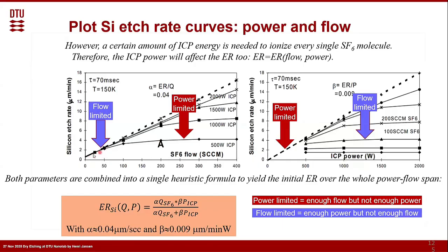Why is that? Well, in the beginning, you have sufficient power at a very low flow regime. There's so much power that all the SF6 will be cracked into fluororadicals, and it means that we call it flow limited. The etch rate will go just linearly up with the flow. But there's a moment where you put in so much SF6 that the power of 500 watts is not sufficient to crack anymore. So a lot of SF6 is just passing by, and it will never get the reaction to create fluororadicals, and it just goes to the exhaust and it's gone. That's where it starts to saturate. Of course, if you then increase the power to a higher value, you fix it at 1000 watts, it can go much further. At 1500 watts, even further, and 2 kilowatts.